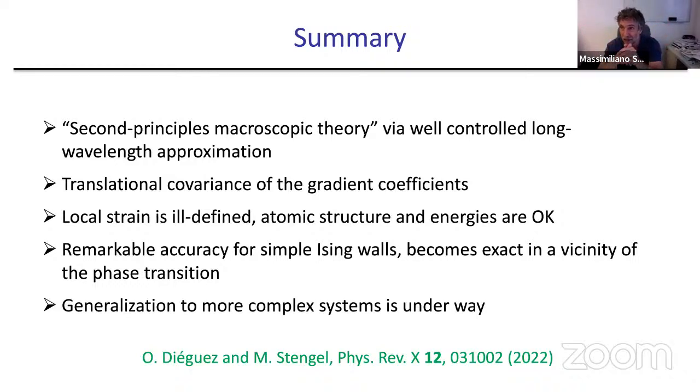And you get three different definitions for the strain for your center of mass, but in the end, if you follow all the prescriptions I discussed for constructing the model coefficients, then you get exactly the same answer. So there is no preferred way, no right or wrong way to choose the definition of the center of mass. They just give you different definitions of the strain that are all equally good.